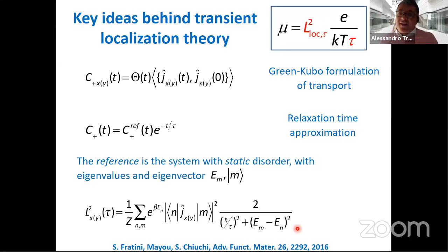The maximum mobility is when the product of the signs is positive. If you do electron, the product of the signs must be negative for the maximum mobility. So it's a matter of interference essentially and quantum effect, but not different than what you would see in band transport. Okay. So thank you.